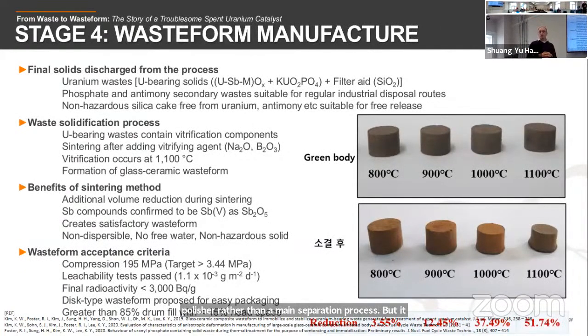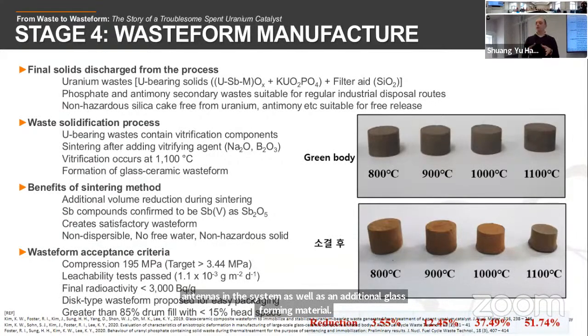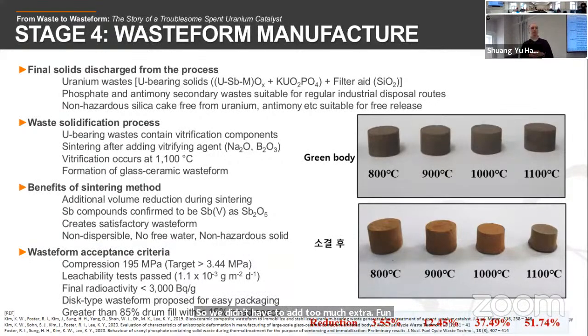Finally, taking all of the solid materials, we actually then needed to solidify them so we can actually dispose of them. Here we settled on using a glass ceramic system, partly because we already had some SiO2 left over from the effluent process that was separated, which was quite good. It allowed us to use that as a raw material in this process. And we found that we could actually also use the antimony that was in the system as an additional glass forming material. So we didn't have to add too much extra final material to these uranium containing wastes.